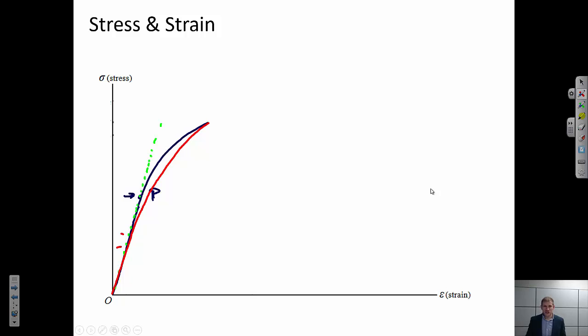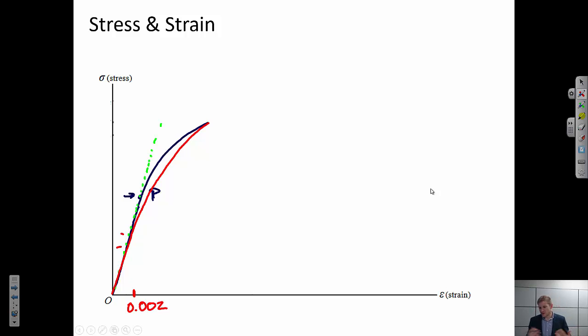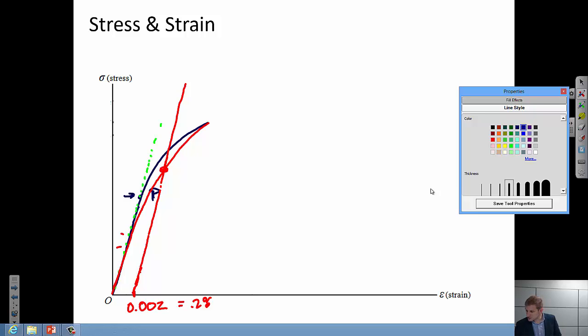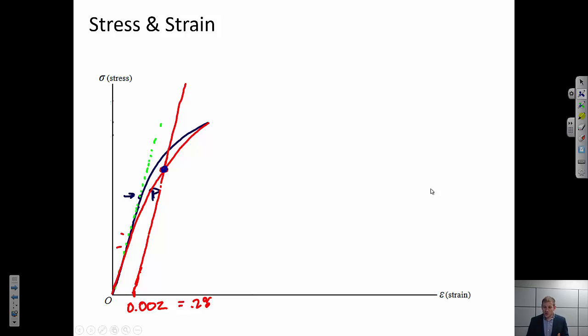We use a convention to illustrate where we're going from elastic to plastic deformation. We start on the horizontal axis at 0.002 strain — that's an agreed-upon value, the same as 0.2% strain, a very small strain. Then I draw a line with the same slope as the initial linear region, but starting from that offset point. Where these two lines intersect is what is commonly referred to as the yield stress, yield point, or yield strength of a material. We use this convention because it's often very difficult to identify a specific point where the curve deviates from linearity.